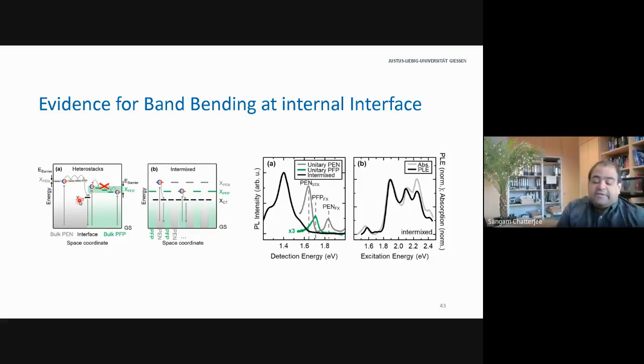The intermixed system should not have this, because, of course, after the pentacene, you have the next perfluorinated pentacene, you have the next pentacene, you have the next perfluorinated species. So there's no way for the molecules to diffuse away. And indeed, if you do the photoluminescence excitation experiment in the intermixed system, which is shown on the very right, you actually see that all the peaks you see in absorption contribute to the emission at the lowest possible energy.